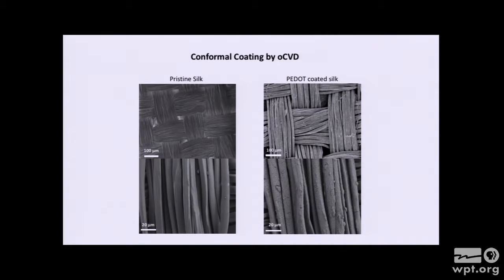So here is some silk material. This is a larger scale, 100 microns. This is 20 microns. So here you can see the weave pattern. Here are the individual fibers. This is the sample before deposition. This is the sample after PEDOT deposition. You can tell the difference. It's kind of hard to tell, not even sure if you can see the resolution, but the coated samples under normal light look blue, because PEDOT, when you form a thick enough film, actually looks very deep navy blue to the eye. But you can also see the roughness here in the SEM.